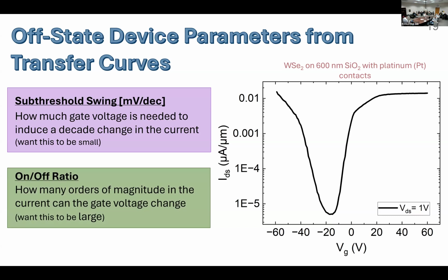The other key device parameter that we can obtain from this graph is the on-off ratio, which tells us how many orders of magnitude in the current the gate voltage can change. Ideally, again, we would want this to be very large. However, in this case, by looking at the minimum off current and maximum on current, we see that it's just a value of 10 to the power of 3.